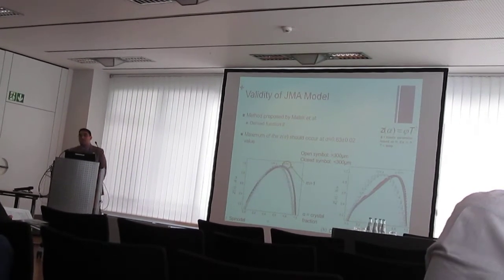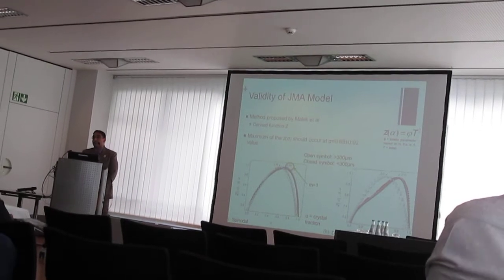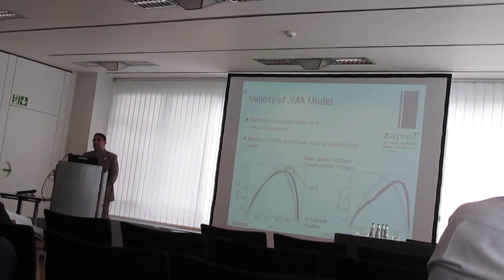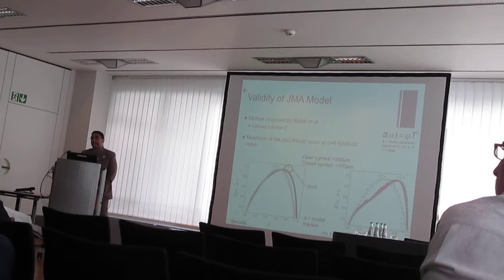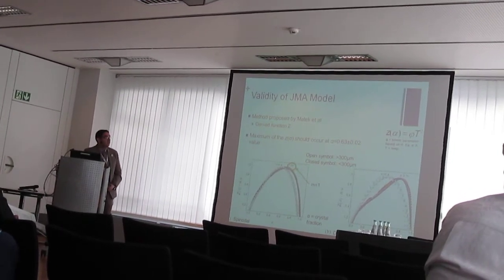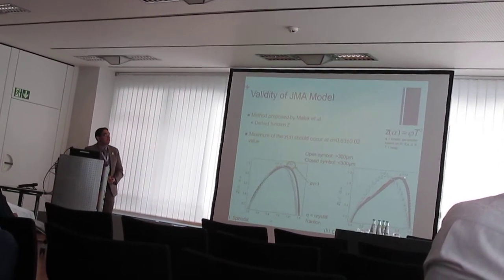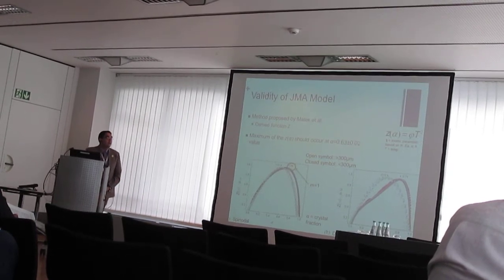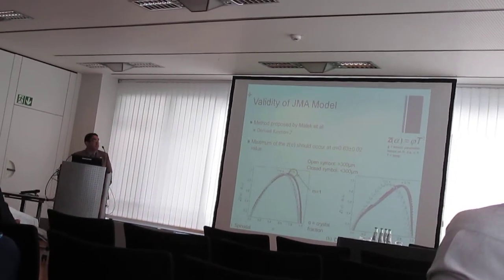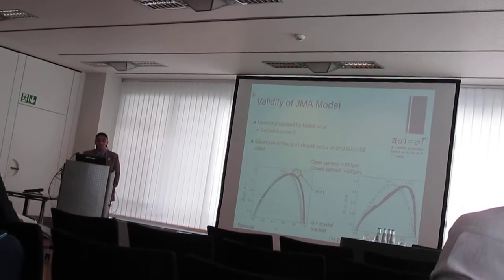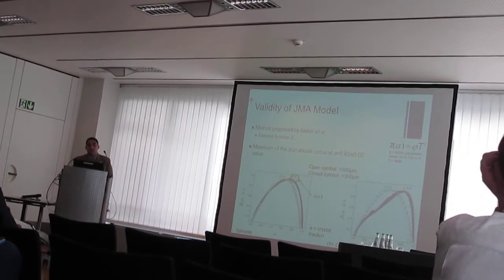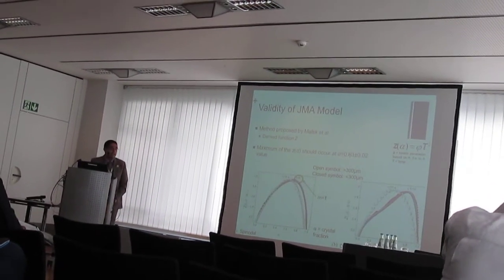So we determined that the crystallization kinetics of these two, the larger size bioglass, could not be described by the JMA equation. We also see that the smaller particle size for droplet phase separated glass can also not be described by the JMA equation because the maximum of the z of alpha curve is not within the given range.